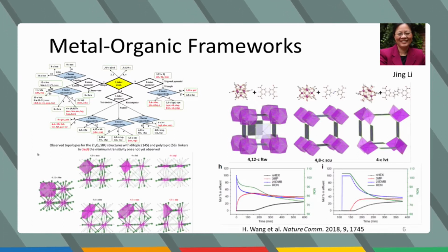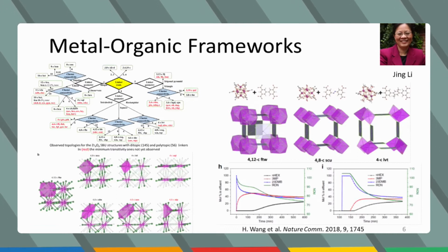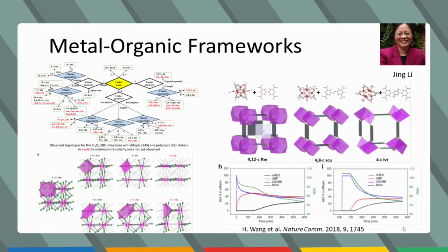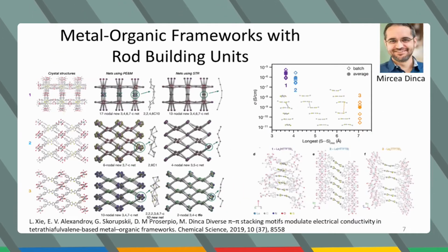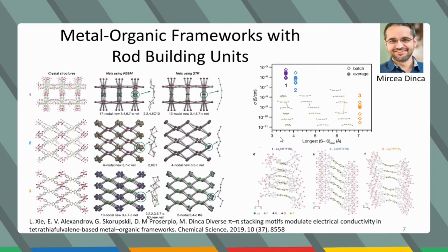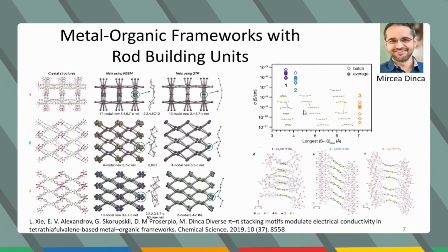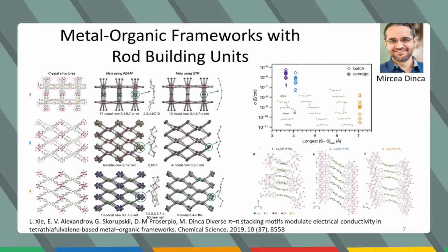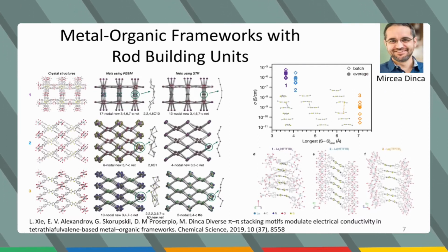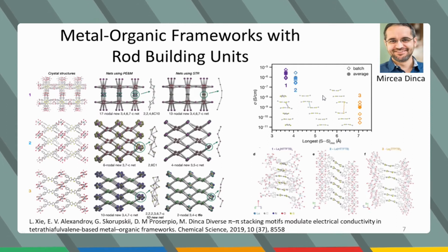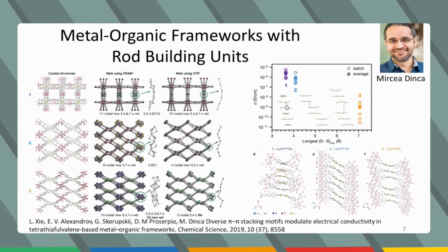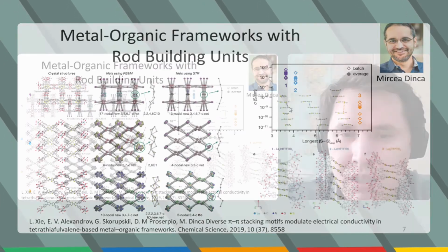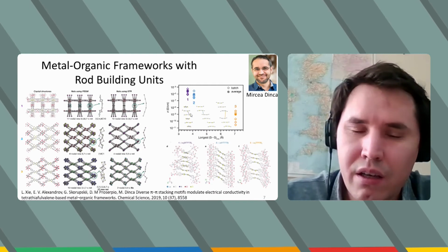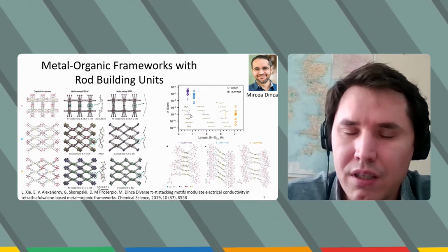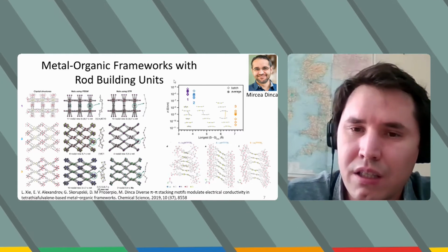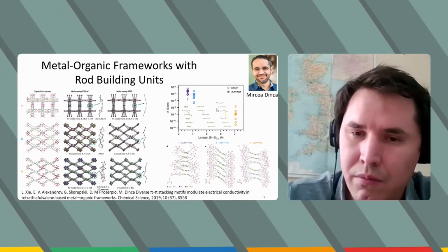adsorption, driving separation of components of oil, for example. And another way to use information about topology is finding correlations with electrical conductivity. For example, in collaboration with Professor Mircea Dinca from MIT, it was found that topological type influences the distance between tetrathiafulvalene linkers, and this distance correlates quite well with the conductivity of new materials.